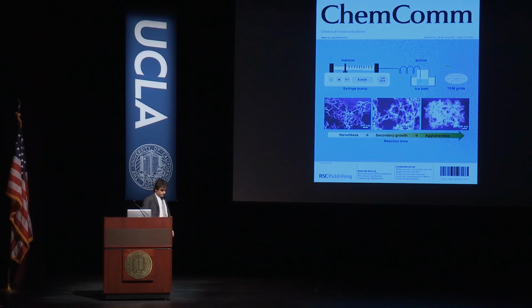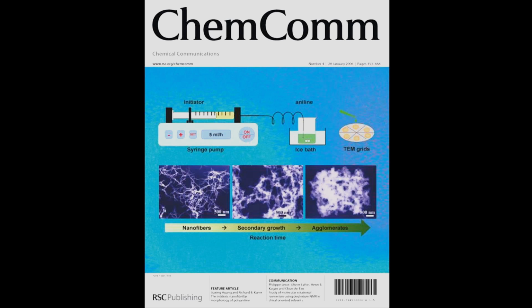We then looked at how everybody else had been making polyaniline. And what they did is they put in 1 drop of acid into aniline. And when we repeated this experiment, with a stopped flow reactor, we found the first drop actually produces nanofibers. And it's the next thing that produces agglomerates, and eventually you get this agglomerated form of the polymer that doesn't disperse and isn't useful. In fact, one of the things that I learned in graduate school is the only reason that conducting polymers haven't been used for very much is, unlike conventional polymers, they don't melt and they don't dissolve.